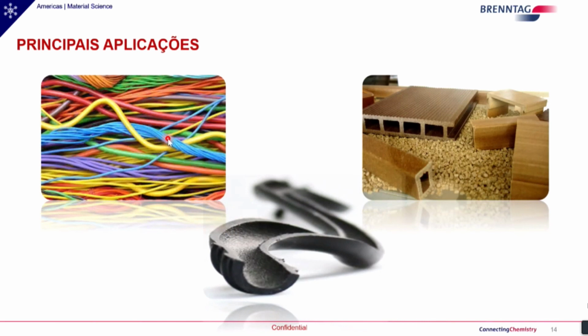In the composites world, we have the migration or the loss of the wood part precisely because there is not a good interaction with polypropylene. This material, after a while, or after it is exposed to the weather, to sun or to rain, has a loss in its surface. It's damaged in the surface, and it's hard to compact it as well. So same thing, we gain in tensile strength, flexural strength with the use of these agents.